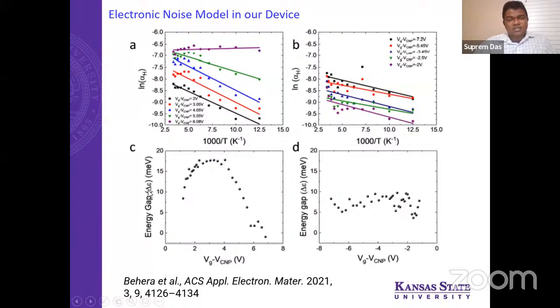So we extracted the delta E, which is the trap state energy, and this is the first time we derived the trap states in this type of high mobility and ultra high mobility devices to be between 5 millielectron volts to 17, 18 millielectron volts, depending on whether you are in the hole state or electron state, but nevertheless between 5 to 20 millielectron volts. So they are really, really small, but by doing this fine experiment, we are able to extract this extremely small energy level of these trap states, and we truly believe that these are responsible for giving this ultra low noise.